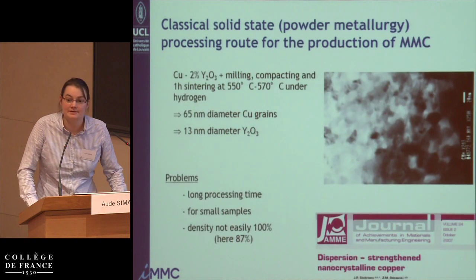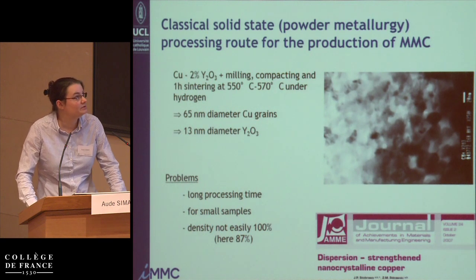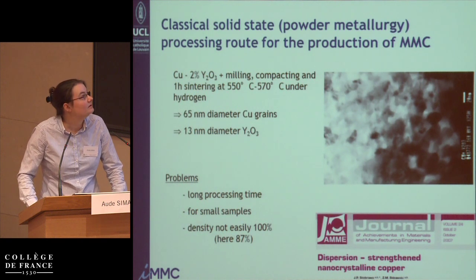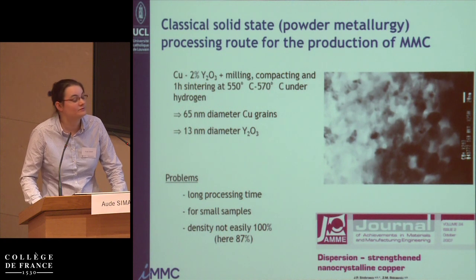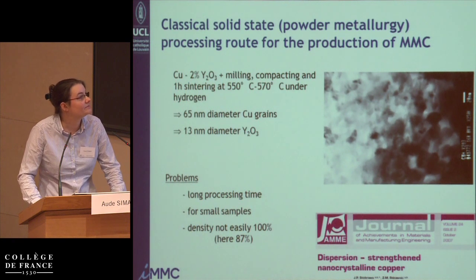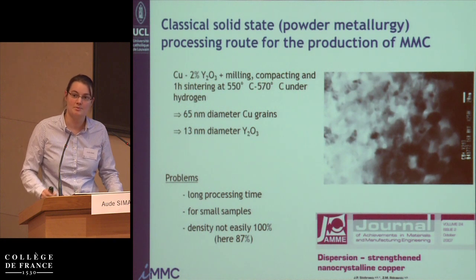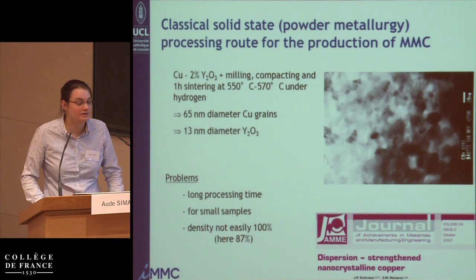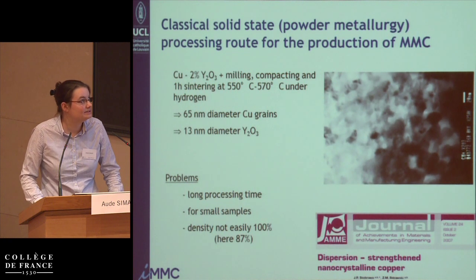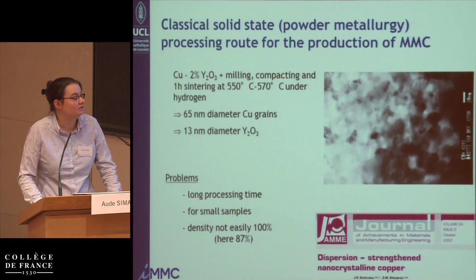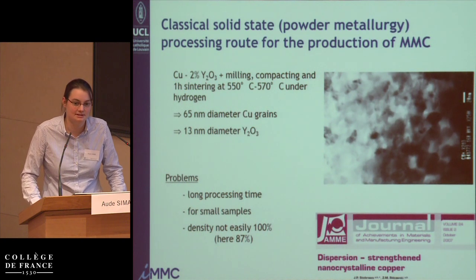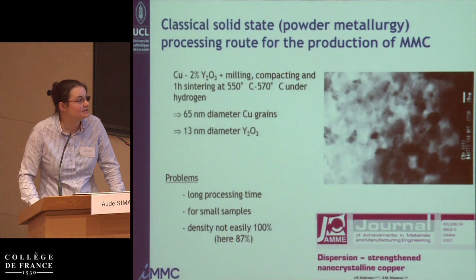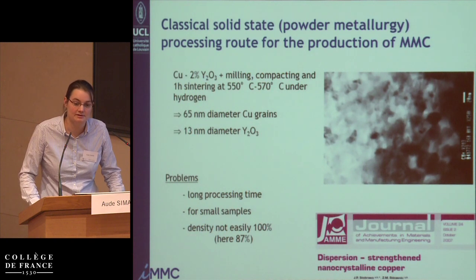That's why it's sometimes interesting to produce these materials by a powder metallurgy processing route. An example here is the production of a copper-based composite with yttrium oxide and with some milling. You put copper powder and yttrium oxide powder, and with milling, compaction, and sintering, you end up with a compact that has interesting properties. You can also do that by spark plasma sintering or other methods, and by spark plasma sintering you probably end up with a better density.